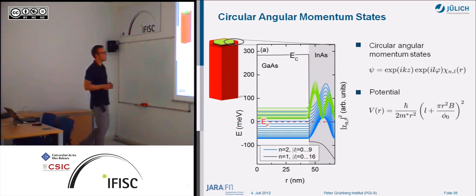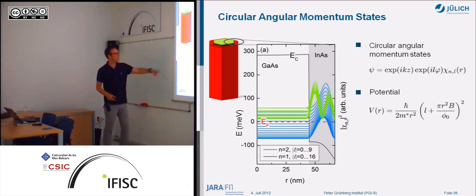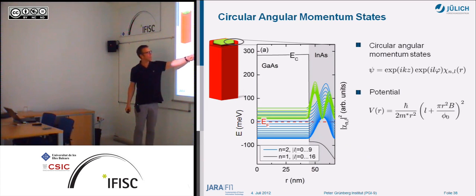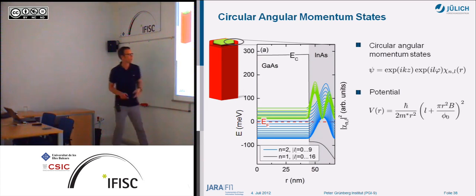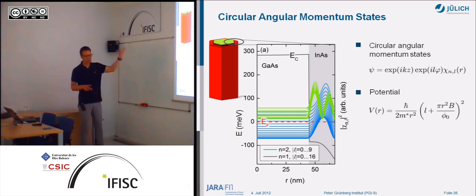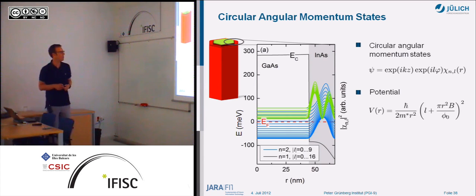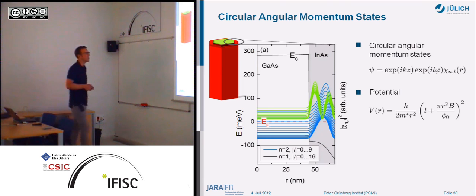So what you get is you have these confined states, and then you have this ladder of states because of the angular momentum. Yeah? So the angular momentum is going from 0 to 9 or 10 or whatever. The Fermi level is here, and fortunately, at least in our calculation, the Fermi level is within the first level, so the first excited states, the green lines here, are above the Fermi level.